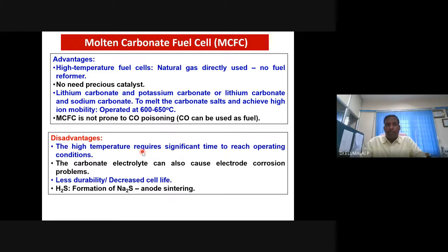And these alkali carbonates provide enough ion mobility or ion conductivity, provided they are heated at this temperature, 600 to 650 degrees. And these MCFC fuel cells are not prone to CO poisoning. They are CO tolerant already, without using catalyst, without using bifunctional catalyst, because CO itself can be used as a fuel. There is no question of CO poisoning because it is high temperature. If at all CO is formed or CO is used as a fuel, it can be easily converted into CO2. So there is no question of CO poisoning. You don't need to have a bifunctional catalyst, etc.